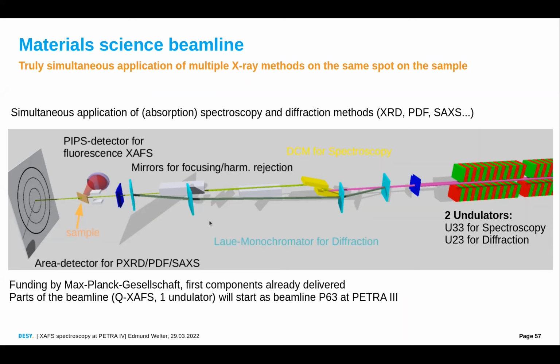spectroscopy beam, as Edmund showed in this visualization of the beamline which I created. This way we can have both energies, for the X-ray spectroscopy and for the diffraction on the sample, and can measure both at the same time. So while we measure XAS with 10 keV, we measure simultaneously a diffraction pattern at 60 keV. It's not optimum because, for example, we cannot measure in transmission mode, because an ion chamber usually reduces the opening angle. So we have to work in fluorescence mode, and then the 60 keV photons always give us a background from fluorescence. The fluorescence will also hit the area detector, so we have to use some energy discrimination in the detector, or if the fluorescence is too strong, even some attenuators for the 10 keV photons.